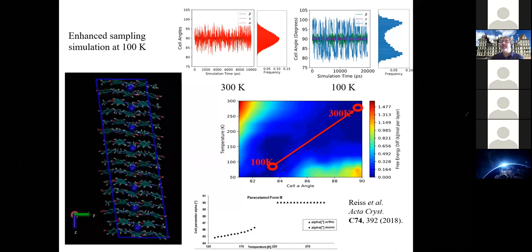And this is a big challenge going forward, because I think there are a fair number of crystals where you need to account for disorder in order to get a real prediction of what the different forms are. And the agreement with experiment as a function of temperature, in terms of what is stable at high temperature and what is stable at low temperature, is actually pretty good. You can see that at low temperature it is the monoclinic form, and at higher temperature it is the orthorhombic form. Okay, so only molecular simulation can give you this, right? So developing simulation techniques that are able to capture this kind of disorder is going to be important going forward. All right, so lots of challenges remain.